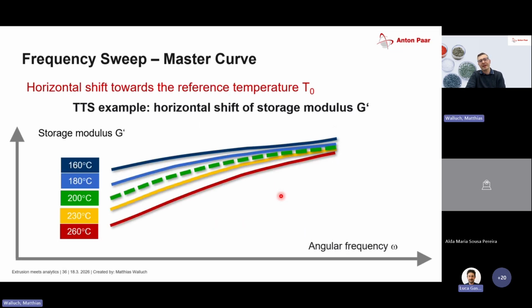There are some other tests that we can perform, which are quite nice and easy. So there's, for example, the TTS. A TTS is nothing else than frequency sweeps at different temperatures and the same material. This can be done with a simple, easy test. So this is not really something complicated. You just start one measurement, and at the end of the day, you get out all the information you want to have and you need. In this case, we did some tests on a polymer between 160 and 260 degrees.